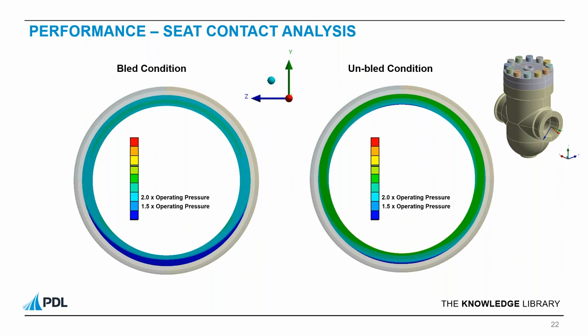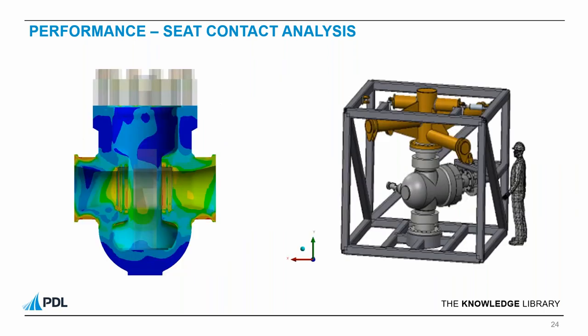So because it's a split gate valve, we needed to look at the bled and the unbled conditions. The images that you can see now are with pressure and actuator forces. The bled has a lower contact pressure, but does remain sealed. Now we can see this contact sealing with the worst case external loading applied. Again, the bled is worst case, but there is a seal maintained, even if it's quite thin down here. The sealing was validated by physical testing and passed first time.